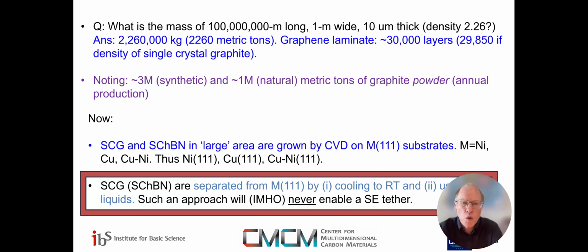Now, currently, what we in the community do is we grow these single crystal layers and then we cool from the CVD growth temperature, somewhere around 1,000 degrees C, down to room temperature, and then we manipulate and play with liquid solvents and so on to delaminate. There's been a lot of very nice work on the films, but this is incredibly slow. So for making the quantities we need for something like a space tether, this is a showstopper, in my opinion.